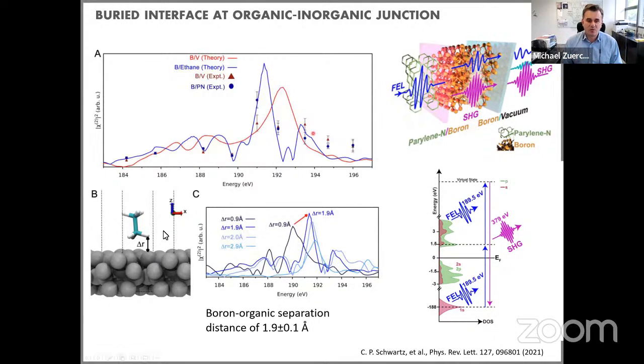So we had to make a compromise and basically do an estimate with a small molecule approaching a surface to estimate at least what the response is. This is why we got a boron organic separation in the range of 2 angstroms. I would say we are pretty certain that's where the shift comes from. But as far as exact quantification for the parallel, I would say be a little bit careful here, because what we actually calculated is a molecule approaching.